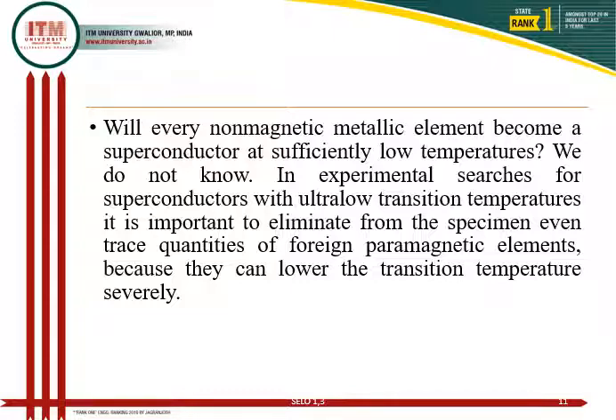We have this query: will every non-magnetic metallic element become a superconductor at sufficiently low temperature? Exactly, we don't know the answer. However, we are working on this. In experimental research for superconductors at ultra low transition temperature, it is important to eliminate from the specimen even trace quantities of foreign paramagnetic elements. If you have paramagnetic elements in the specimen, then they can severely reduce the transition temperature, and we are always interested in increasing the transition temperature. So that is interesting.